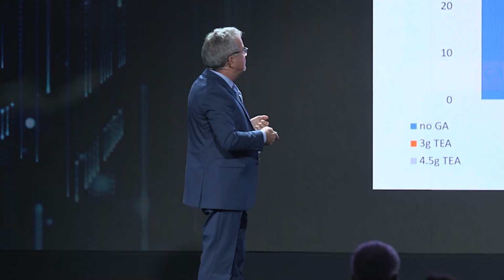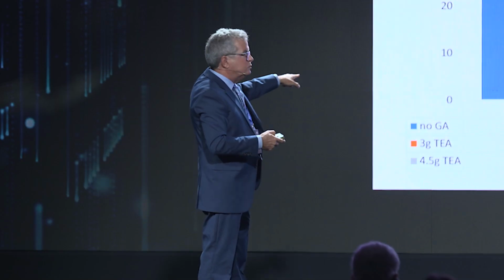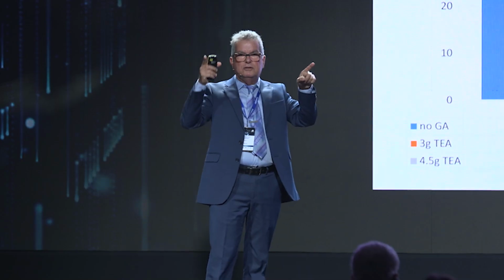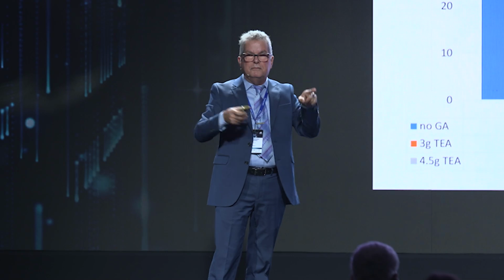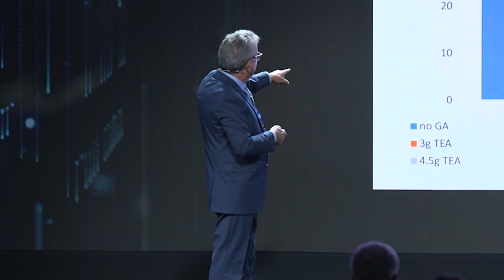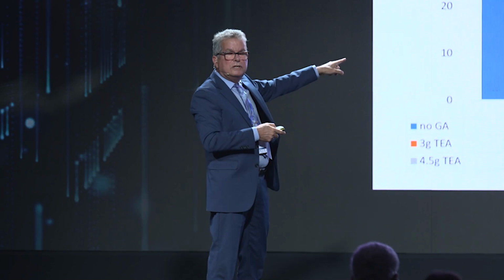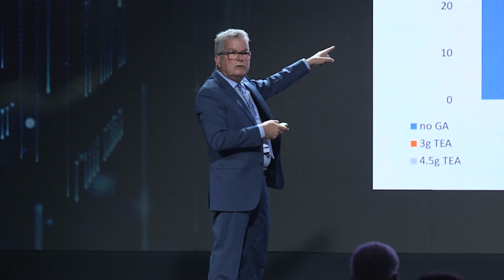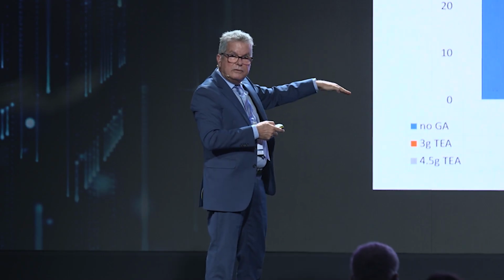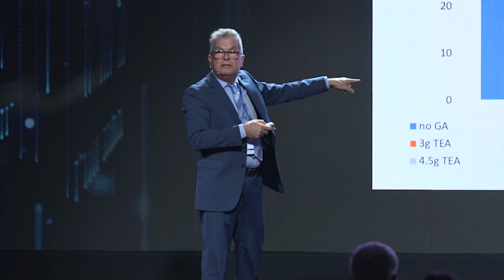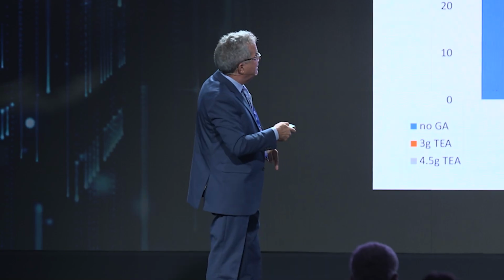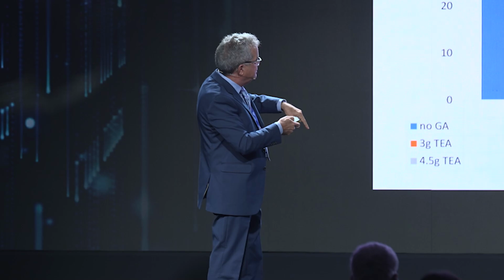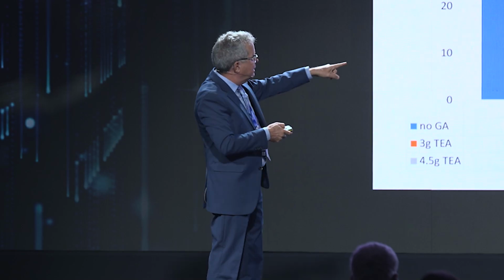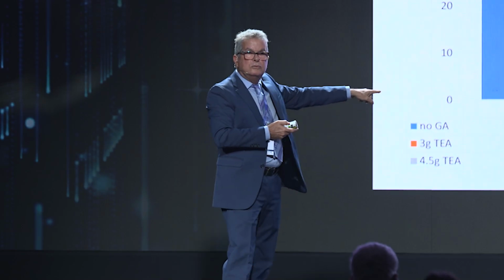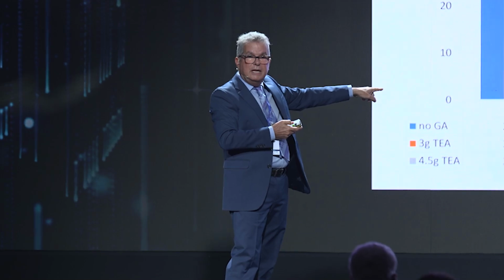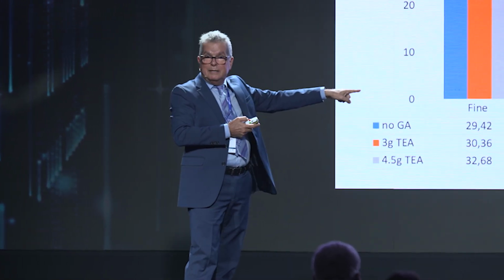And only by doing this, when you check here, we were able to sort out the different fractions and to measure the amount of clinker in the different fractions, and we were able to see that if you increase the dosage of grinding aids, you increase the amount of very fine clinker, on the 7 microns, at the cost of reducing the very coarse clinker. And this is having an impact there. You see, you're able to raise the strength from 8 megapascal at one day to 12 megapascal at one day.